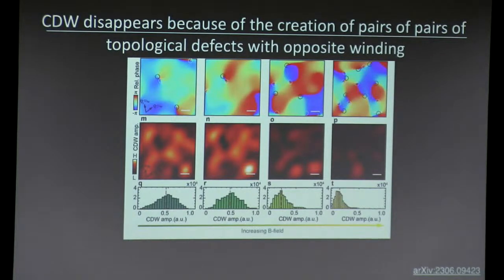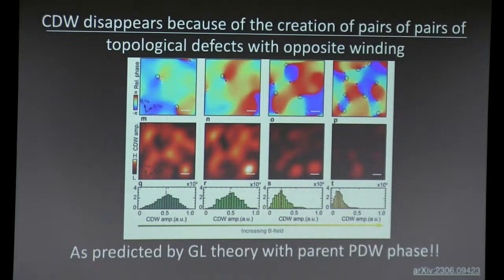We can see that this is happening in real space. As you increase magnetic field, you're generating more and more of these point dislocations - by the way, these are topological defects. You're generating more and more of these topological defects. They come in pairs with opposite winding, and their numbers grow. At the position of each such dislocation, the amplitude of the CDW order parameter goes to 0. This is how the charge density wave gets killed with a magnetic field, and this is predicted by the Ginzburg-Landau theory.